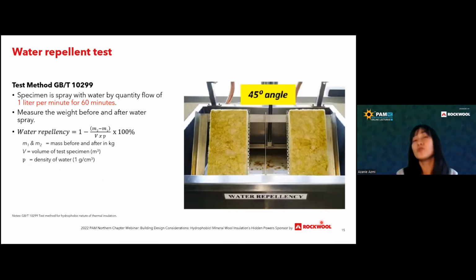The third, we also do a lot of other tests, not just one or two, just to make sure of the water repellent performance. This is actually GB/T 10299, which is the test method for hydrophobic nature of thermal insulations. How we do the test is, you have the sample at 45 degrees, you run the water at 1 liter per minute for 60 minutes. And after that, you check the weight before and after.